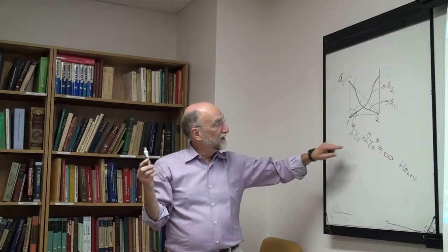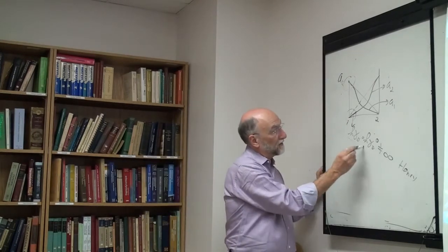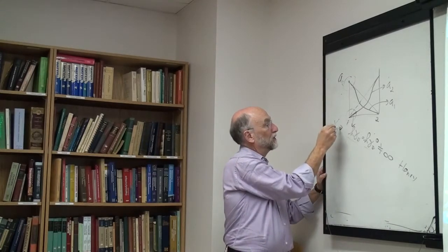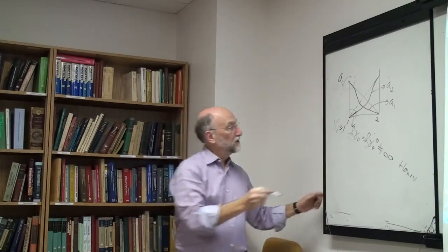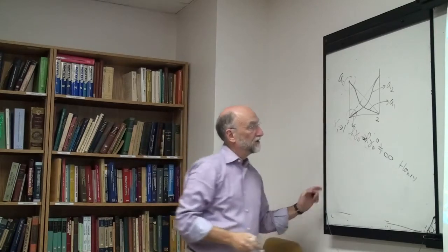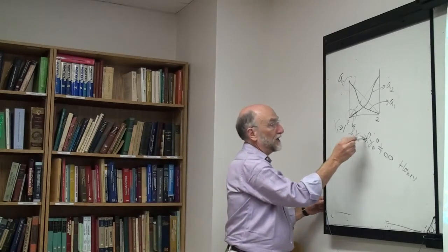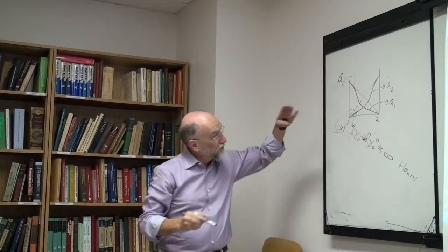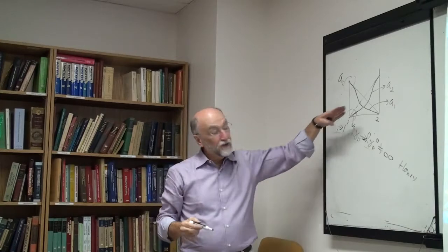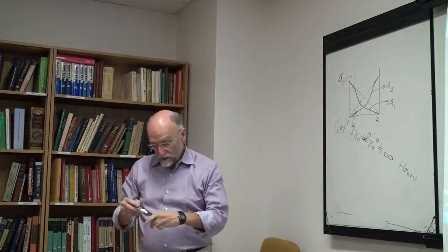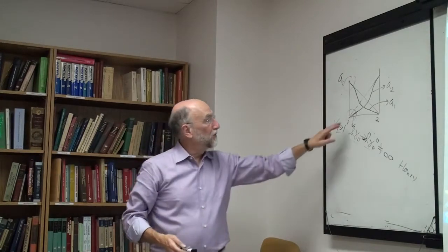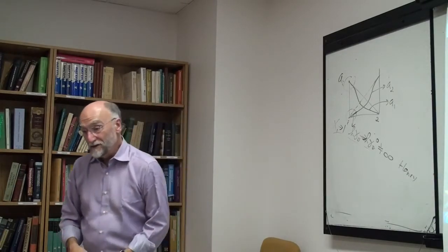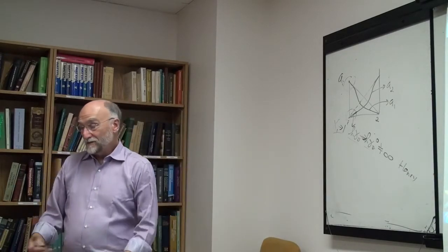Okay, this is Henry's law: as x1 approaches 1, log gamma 2 approaches a constant, log gamma 2 Henry. Log gamma 2 Henry is the limiting slope at x1 equals 1, and it's not equal to infinity. There's a finite limiting slope. Physically, what this means is if you take pure component 1 and you add an atom of component 2, you don't get an infinite change in energy. You just get a slight change.